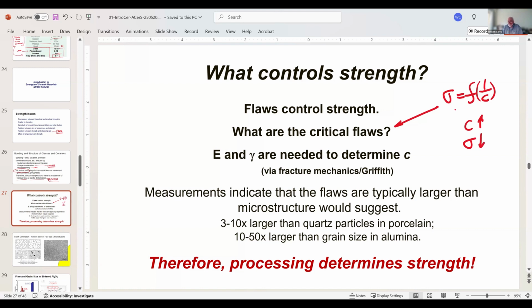Okay. So if I have a specific strength level, say 200 megapascals, I could calculate what the flaw size would be necessary. And I would have to stay below that flaw size to maintain 200 megapascals. I need elastic modulus, and I need something called a fracture surface energy to determine the size of my flaw. And that's under a criteria called a Griffith flaw criteria, which we're going to talk about. But in this ceramic world, we have this argument about flaws that is misguided, and I will show you that. We find in porcelains, everyone says oh, quartz controls the strength, but I find that my strength suggests quartz particles that are 3 to 10 times larger than they actually are, suggesting a cluster. And in alumina, it's 10 to 50 times larger than the grain size, and I will show you data to back that up. So what we get out of this is that processing determines the strength.